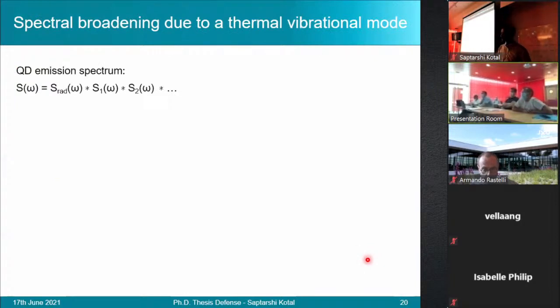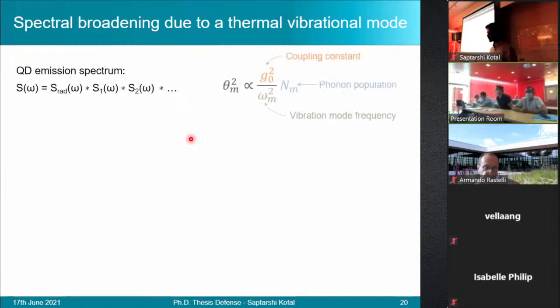Then the photon emission spectrum S of omega can be calculated as the convolution product of the radiatively limited line shape, which is S_RAD, with the individual contributions to the broadening brought by every individual vibration mode. So for a given vibration mode m, we have S_m of omega, which is governed by the following parameter, which we name theta m squared. Theta m squared itself is dependent on the coupling strength, the vibration mode frequency, and the phonon population in the mode.